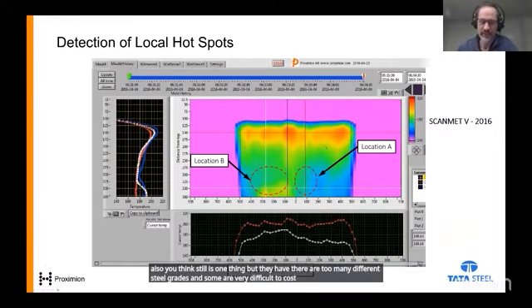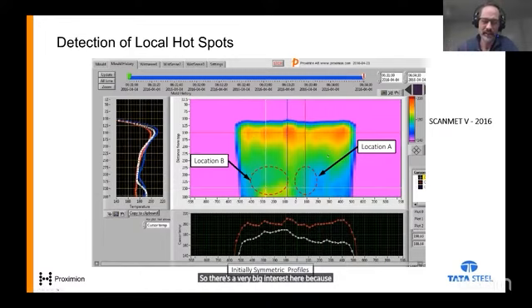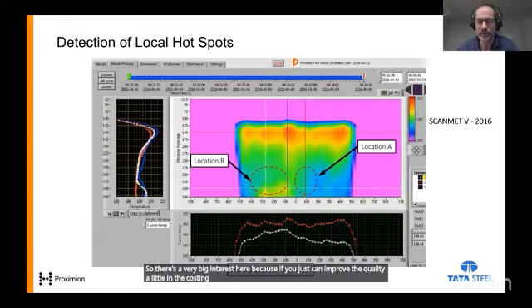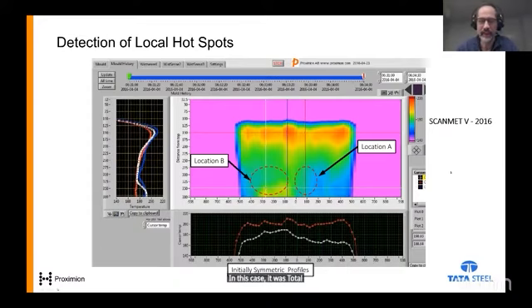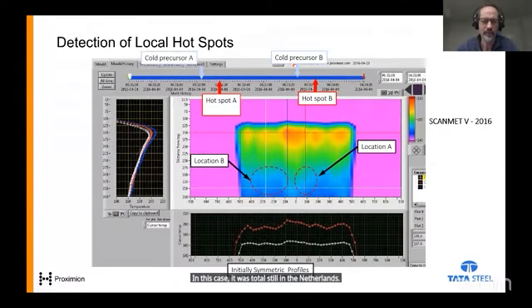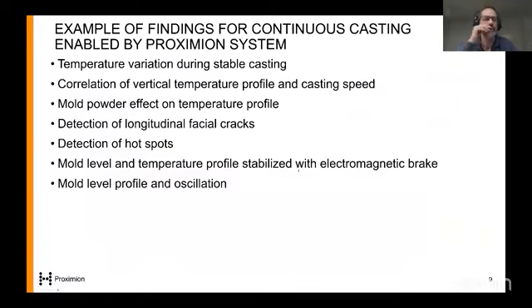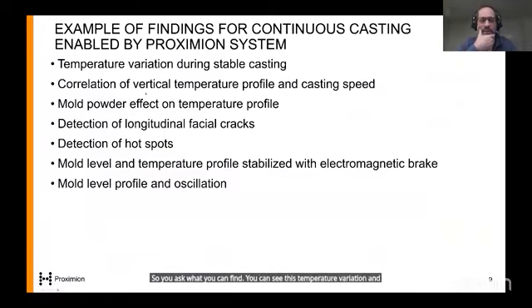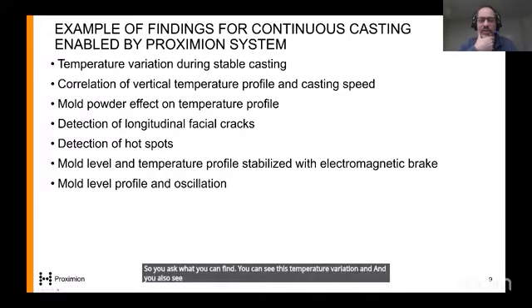So there's very big interest here, because if you can improve the quality a little in the casting, that's the most critical stage, and that's worth a lot for the plant. In this case, it was Tata Steel in the Netherlands. You can see this temperature variation, and if you change the casting speed, you can also see how that affects the solidification by monitoring temperature.